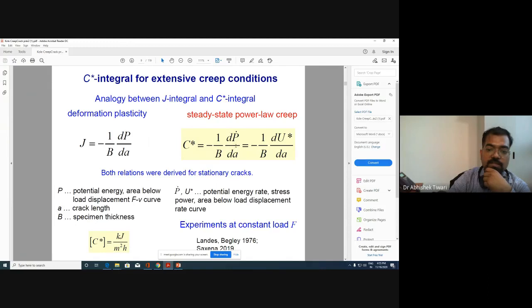You can just appreciate that in C star, instead of the change of potential per unit crack length, we take the change of rate of potential per unit crack length, because we have a time dependence involved. So similar to the formula we discussed for the J integral, we have formulas for finding C star experimentally. We will stop the lecture here, and then we will discuss further the experimental calculation of the C star integral, and we will also see the effect of small creep zone and extensive creep zone on the C star integral we calculate. Okay, thank you.